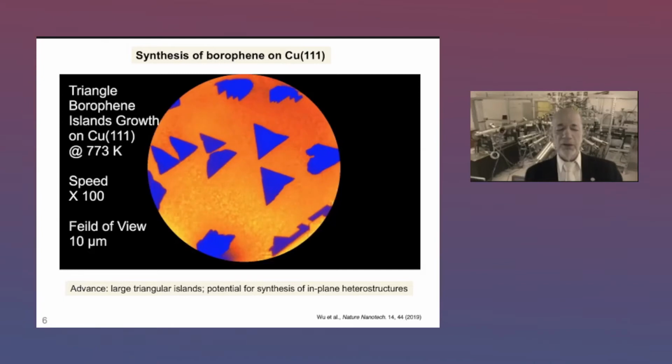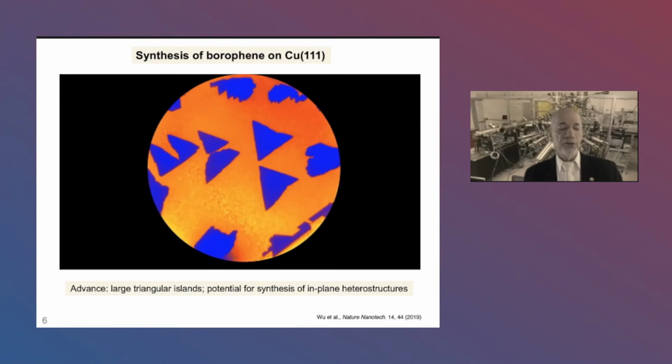However, when we have better substrate with larger terraces, then nucleation can happen in the middle of the terrace, and then the islands tend to grow triangular. For a theorist, this one movie contains a PhD thesis worth of information about surface mobility, growth energetics, etc. On the technology side, this opens the prospect of fabricating in-plane heterostructures.